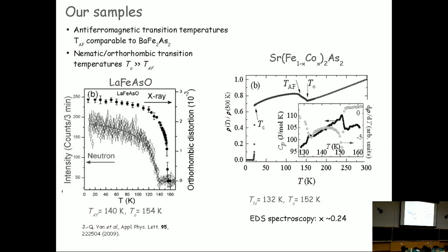You have a first transition at 20 Kelvin, which is the superconductivity transition temperature, and then resistivity also shows this characteristic peak at the magnetic ordering temperature, and then there is another feature which is marking the structural transition temperature. We can see that more clearly in the derivative of the resistivity. You have clearly the 2 negative peaks, marking the 2 different transition temperatures.